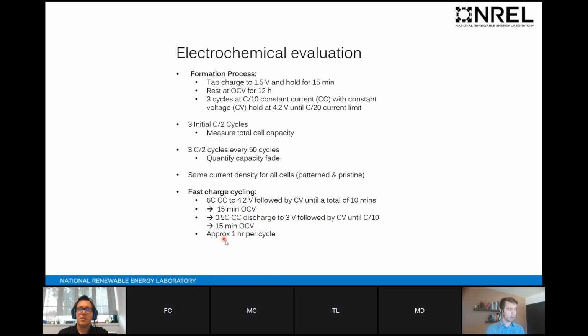And each cycle took approximately 1 hour. So obviously the 0.5C discharge doesn't reach the full capacity, otherwise that would take 2 hours, because the 6C in 10 minutes doesn't reach the full capacity to discharge.